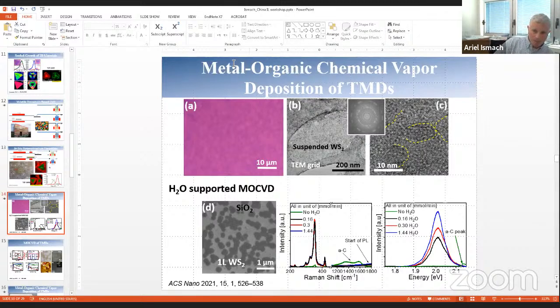The problem with these precursors is that they thermally decompose at relatively low temperatures, and therefore the density of nucleation in this case is huge. And we end up, as you can see here in these three images, with basically nanocrystalline films. Here this film was transferred to a different substrate. The purple color is the color of the target substrate, which is 300 nanometer silica on top of silicon. This is TEM and this is electron diffraction.